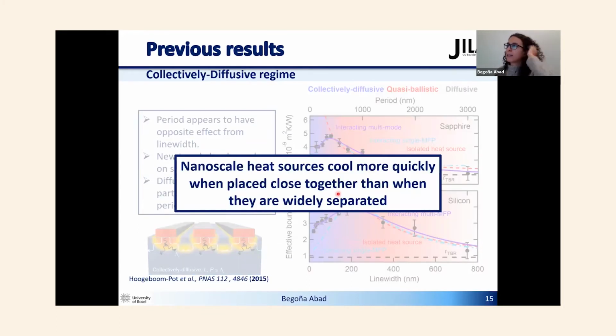So from these studies, we could see that the nanoscale heat sources cool more quickly when placed together than when they are widely separated. And this was called the collectively diffusive regime.